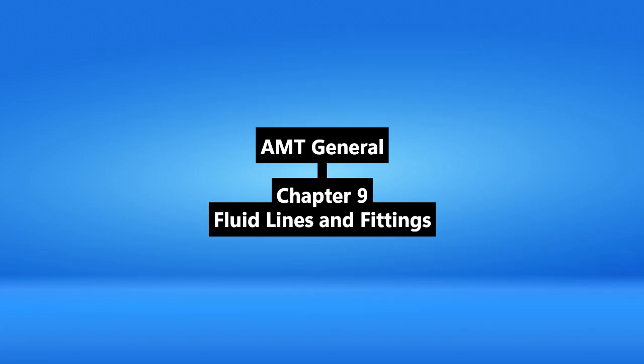Lower stress, lighter alloys, higher demands, stronger materials. That makes perfect sense. Now, steel, that sounds like it's reserved for when things get really demanding. Exactly. Corrosion-resistant steel, or CRES. You'll see grades like 304, 321, 304 1/8 hard. That's the go-to for high-pressure hydraulic systems. We're talking 3,000 psi and above. So landing gear, flaps, brakes, and it's absolutely essential in fire zones.